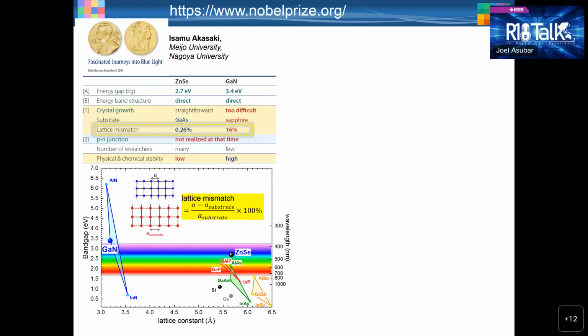Actually, during the 1970s, two semiconductor material candidates were considered for blue LEDs: gallium nitride and zinc selenide. Considering the relative ease of growth of zinc selenide, because it can be grown readily on the readily available gallium arsenide substrates, zinc selenide was much more popular than gallium nitride during those earlier days of the research. The only viable substrate for gallium nitride during that time was sapphire, which has a very high lattice mismatch of about 16% with gallium nitride.